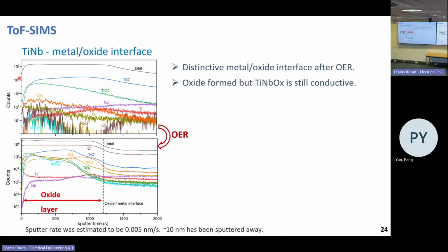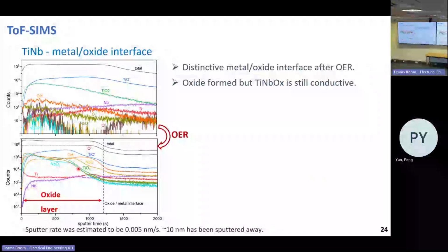In terms of titanium niobium alloy, we can see a distinctive metal oxide interface after water oxidation, and this oxide layer is just a few nanometers, so maybe it's still very conductive for charge transport.